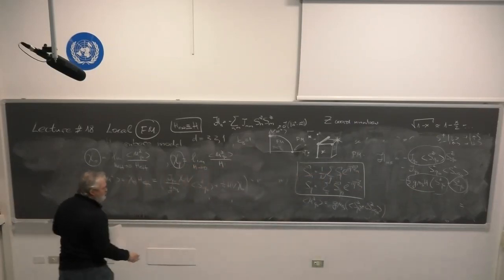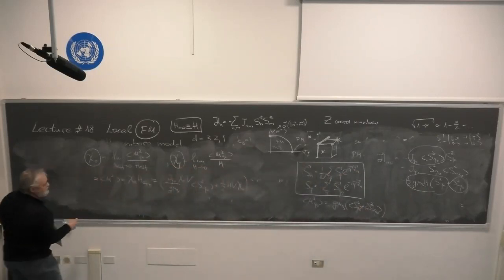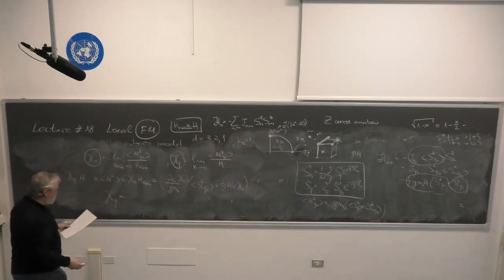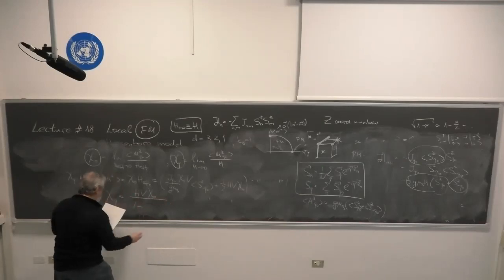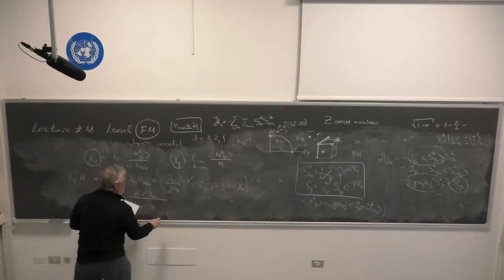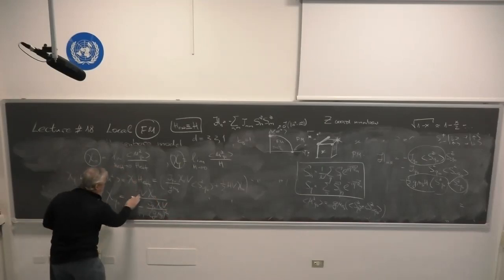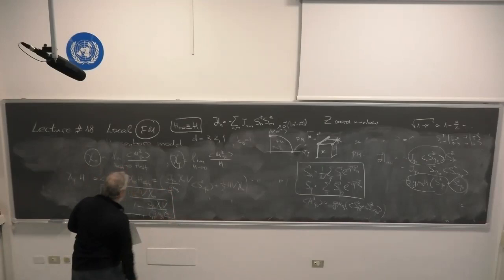As a result, since I take into account the Q naught and minus Q naught components at the same time, this is chi_Q times H. Therefore, I obtain that chi_Q is equal to V chi naught divided by 1 minus J_Q naught chi naught V divided by g mu_Bohr squared. Sorry, this is magnetization. If I divide, H cancels out from the numerator.